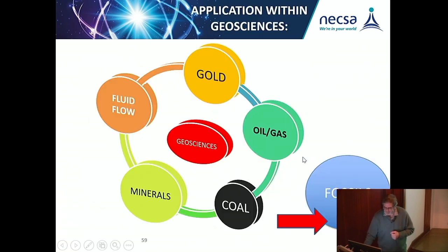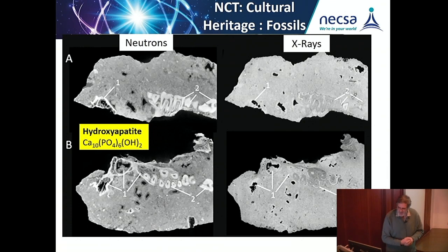Okay, so the last part is I have to look at fossil materials, because in essence these are also geoscientific related. The main thing is why we use neutrons and X-rays, and why neutrons are more effective in finding fossil materials. The fossil has hydroxyapatite with hydrogen within that matrix. So when it's fossilized within the breccia material, and this is a slice of neutrons and a slice of X-rays of exactly the same sample, you can nicely see the signal from the neutron scan is much better than the signal from the X-ray scan.